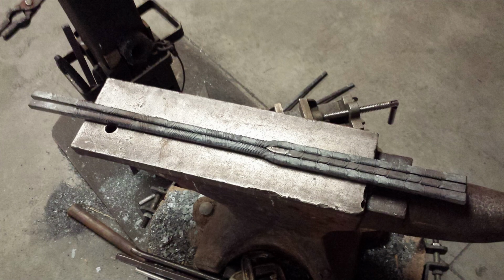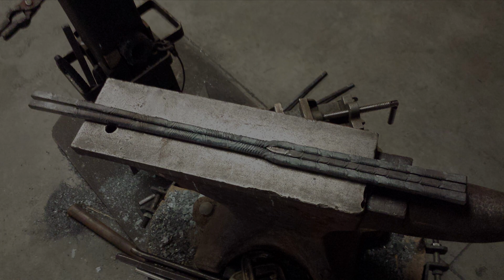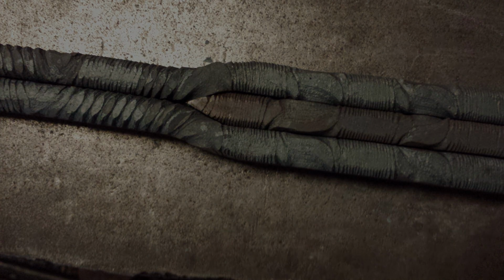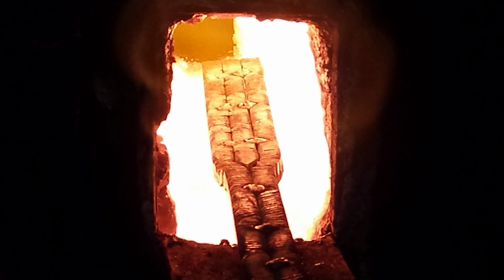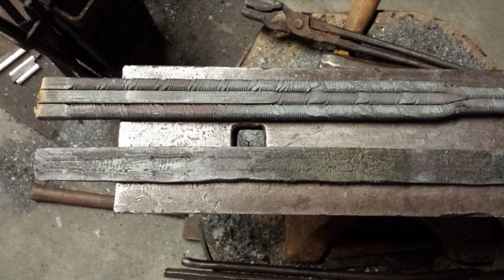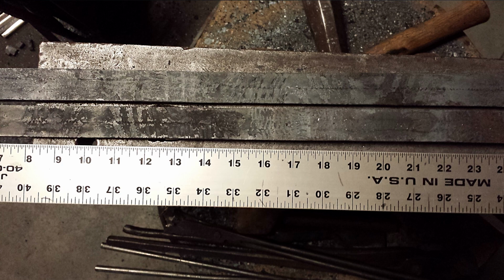This is how I was planning to forge weld the opposite side. The transition between the patterns was easier to forge weld this way. At the top, the serpent side was ready to be welded, and at the bottom, the opposite side was already forge welded. As you can see, the transition zones were looking like the original blade. Here and here.